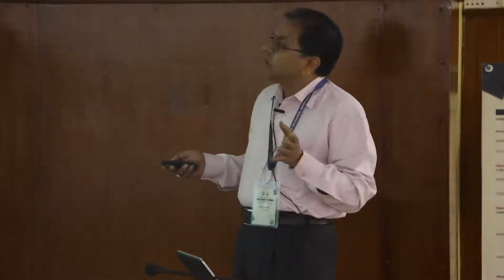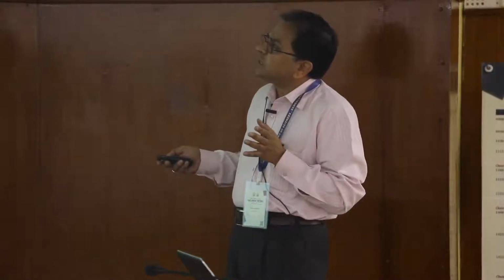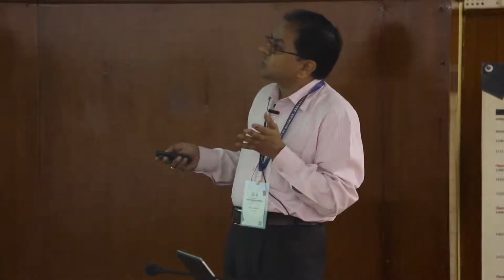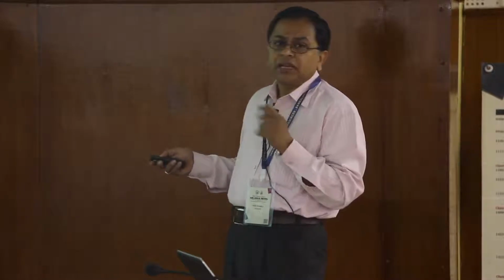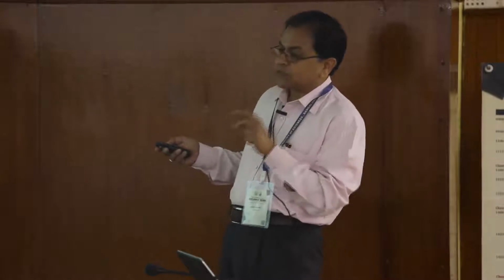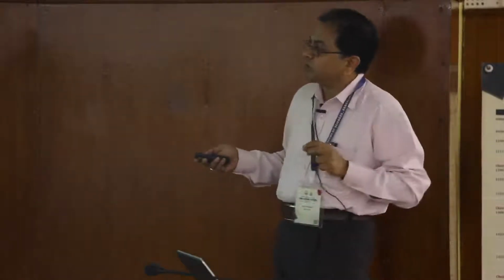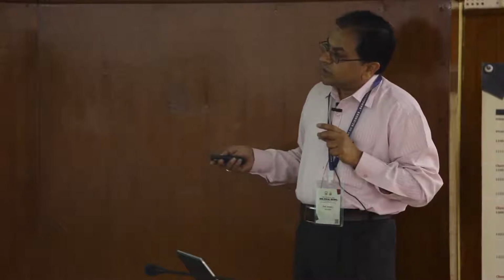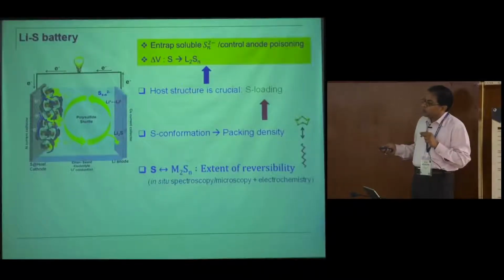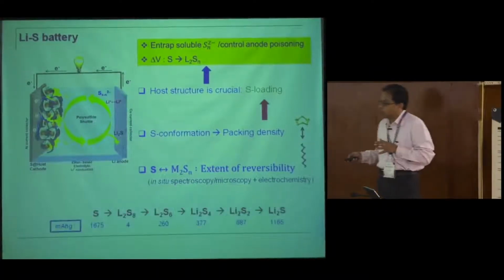What we found out in all our studies is that there are 4 critical points. One, of course, is that the structure is very crucial in loading. Then, of course, how the sulfur sits, because there are a lot of confinement effects in the pores of the encapsulant. And then, using a lot of in operando experiments, spectroscopy, microscopy, both at the lab and at the synchrotron level, what we observe is the incompleteness of the reaction and so on. So that leads to lower capacity.